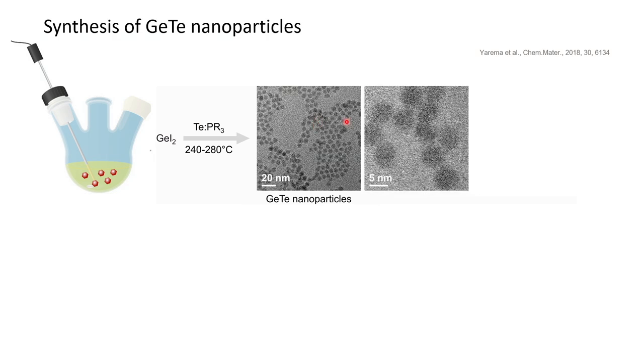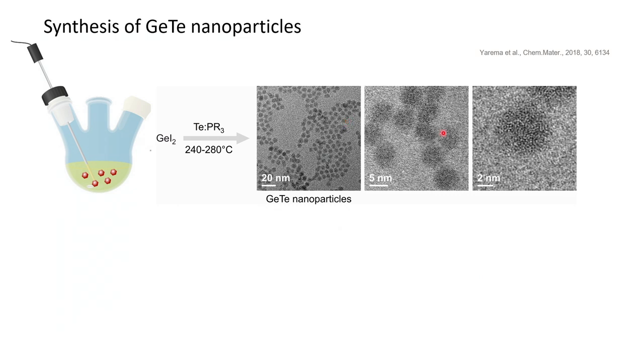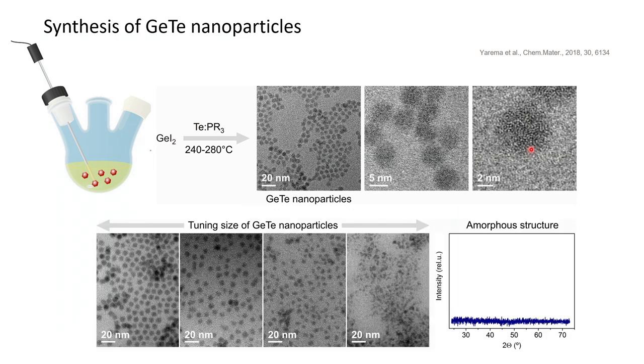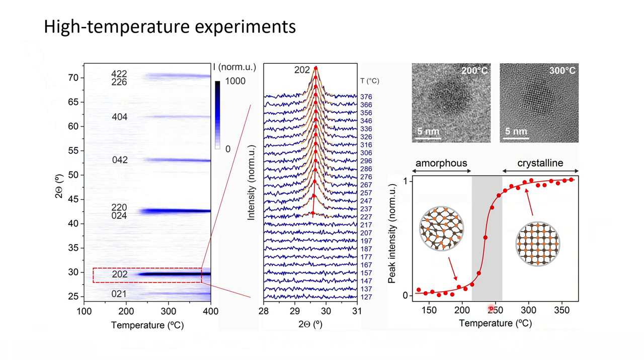But when we look at them closer, and even more closely, we were like, all right, there is no atomic order for these materials. We don't really see any atomic arrangement if you look close up at them. Otherwise, the nanoparticles are like normal. We can tune the size of the germanium telluride nanoparticles. The composition contains germanium and tellurium, but they have an amorphous structure, which is shown here by X-ray diffraction having no peaks. So then we decided with Olesya, what shall we do?